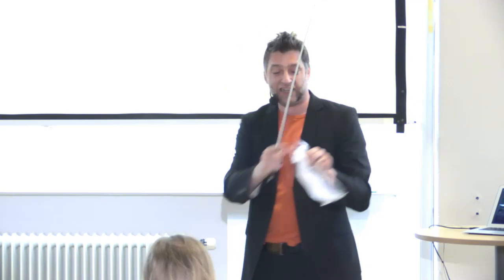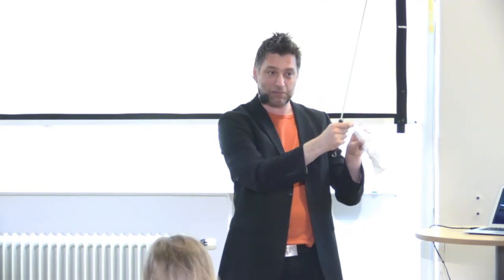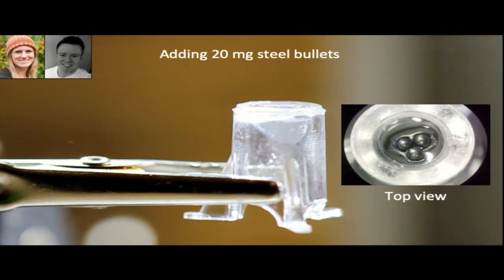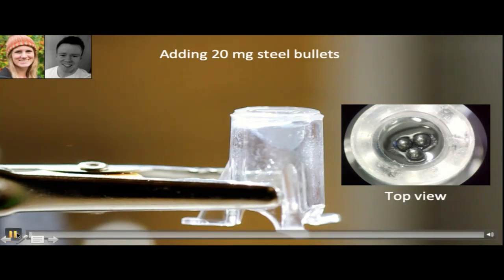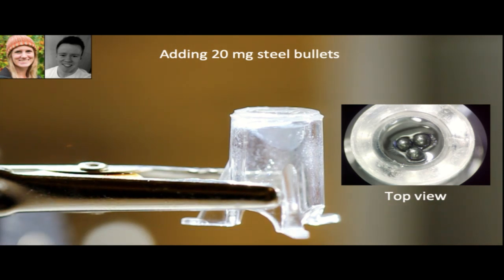It's maybe 10 times as thin as human hair. So this kind of plastic foil is typically of the size 20, 50 micrometer. So the films we're making here are 100 times thinner than this. But still, they're extremely, extremely strong. So we're going to see how strong they are by just loading metal bullets on them. And every bullet we add, every bullet is 20 milligrams.